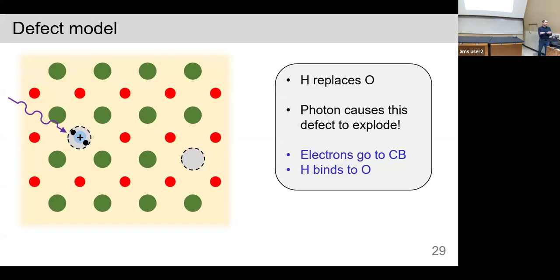Well, here's our defect model. And the other clue was that it only works if you anneal or bake the sample in hydrogen. So hydrogen is key. So when it's annealed in hydrogen, hydrogen replaces an oxygen atom. What that means is that the hydrogen is occupying the oxygen site. So these red atoms are oxygens. Now, essentially, this is a proton and 2 electrons in a site that otherwise would be an oxygen atom.